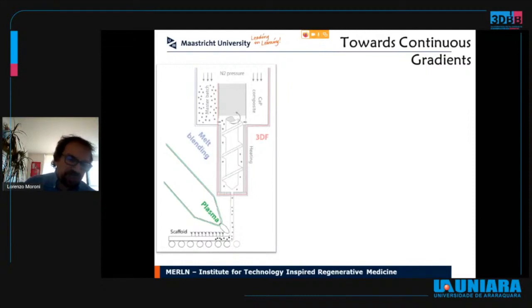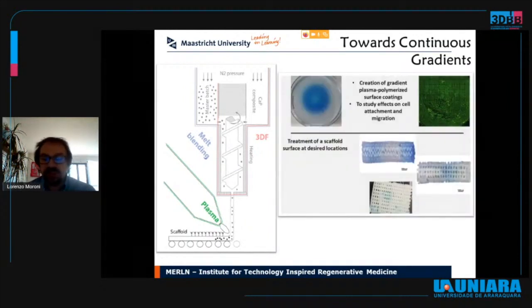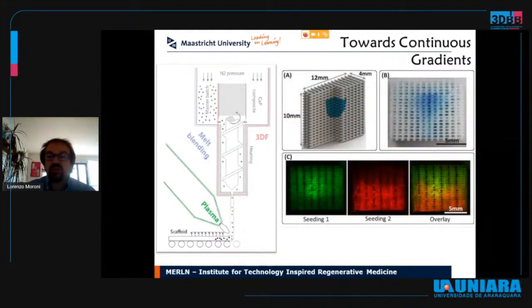We have also further increased the level of control, in space and time, of cell adhesion of these scaffolds with the integration of an atmospheric plasma torch, which has allowed us to really change the hydrophilicity and hydrophobicity of the scaffolds, therefore creating local areas of adhesion versus local areas of non-adhesion within the scaffolds. You could imagine that it could be used, for example, to seed two different cell populations, which can therefore recreate a more complex tissue interface in regenerative processes. Here, think about the osteochondral interface, where cells typically would be more rounded on the cartilage side and more spread on the osteogenic side.